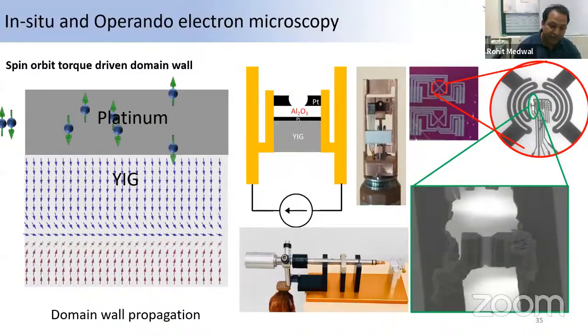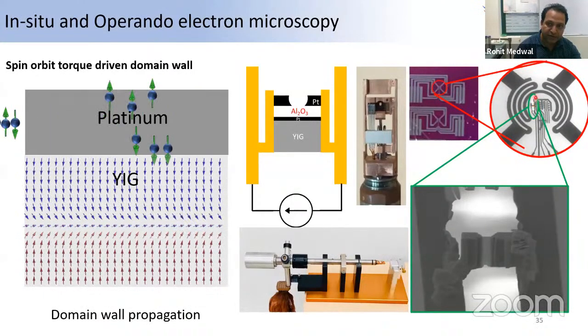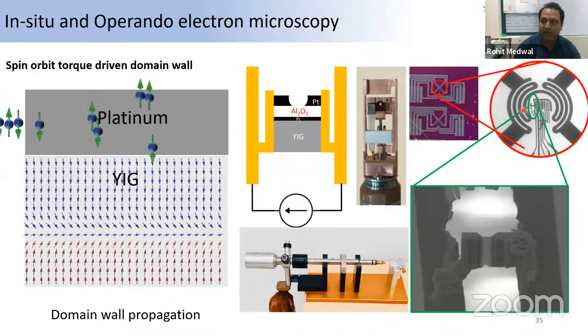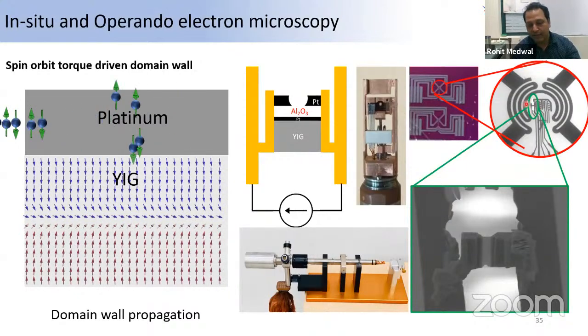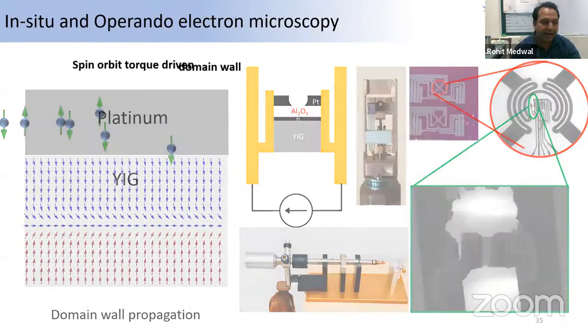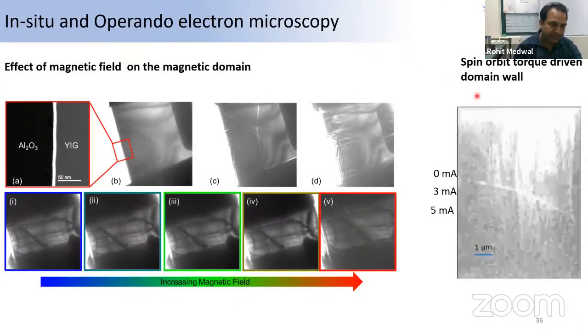We integrate this device on the chip. You can see this very white dot. This is the real device, which is 1 micron, and we put it in the TEM, and we clearly observe these results, which are quite interesting. You can see here that this is the YIG film, which is just a normal image. And under the focus defocus image, we can see this is the magnetic domain.